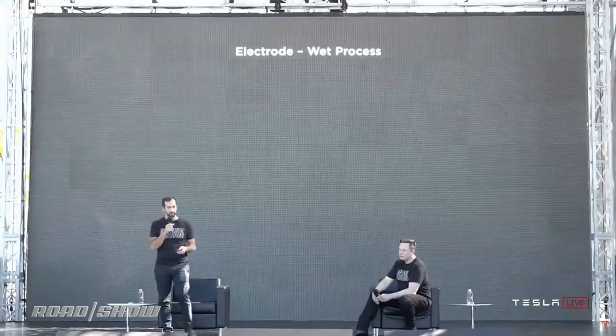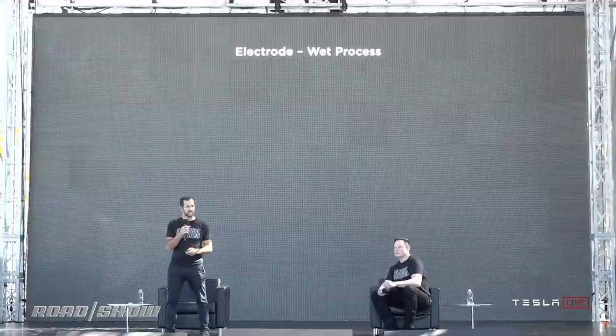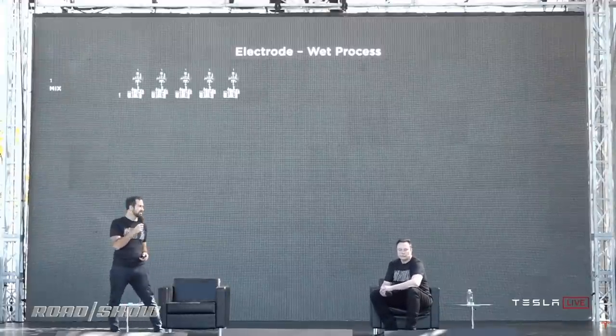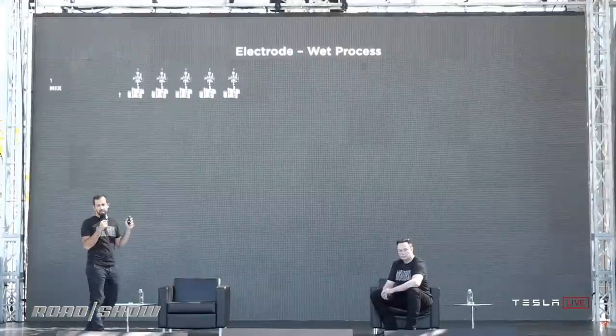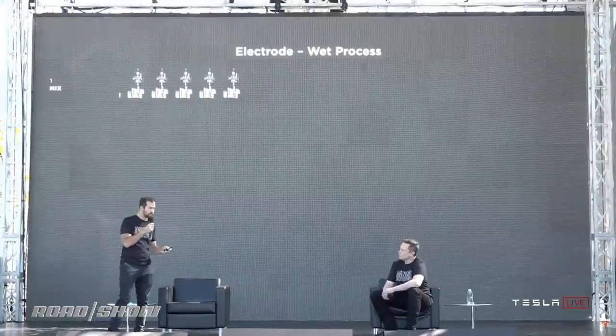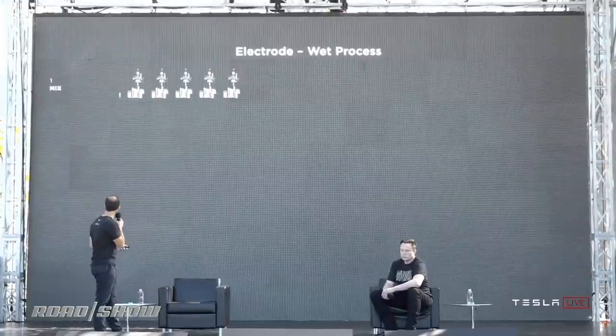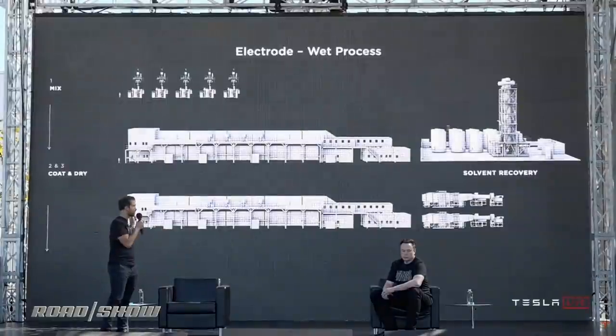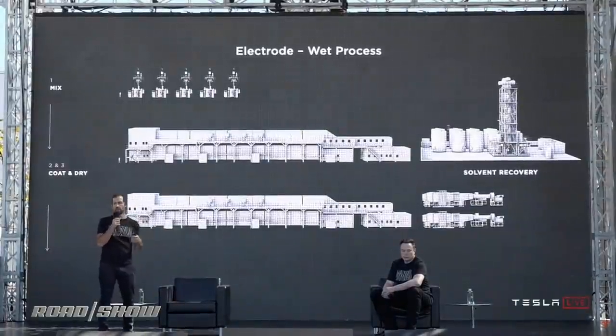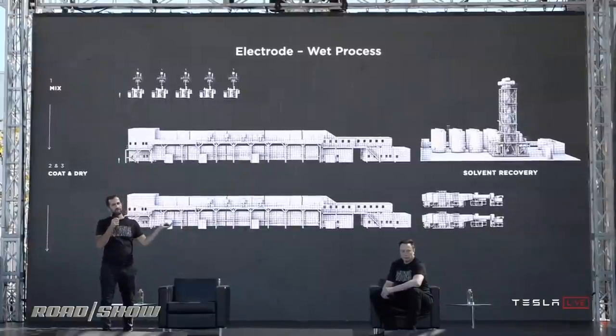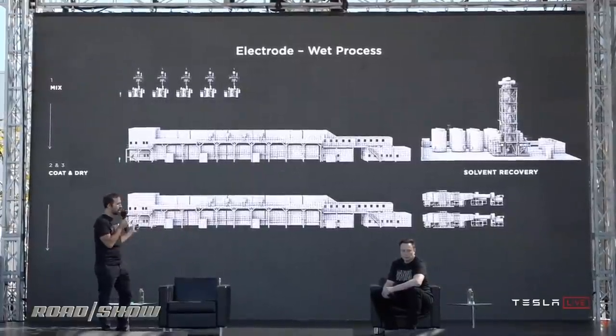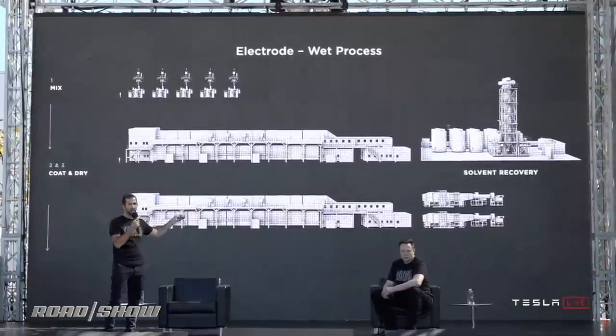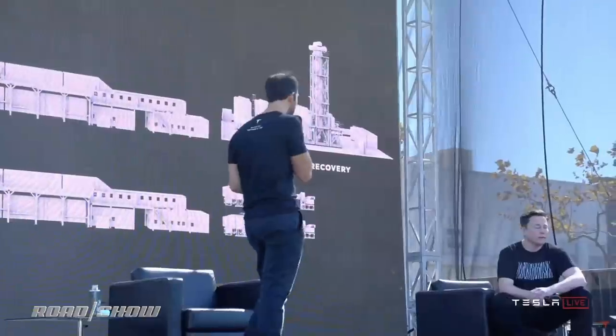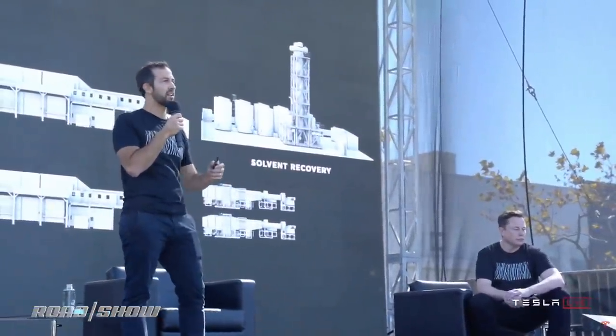And one of the most important processes is where it all begins, the wet process of the electrode coating. And just to give you all a sense of scale, I'm going to walk through what's in that wet process. You've got mixing, where the powders are mixed with either water or solvents for the cathode. That mix then goes into a large coat and dry oven where the slurry is coated onto the foil, huge ovens, tens of meters long, dried, and that solvent then has to be recovered. You can see the solvent recovery system. And then finally, the coated foil is compressed to the final density.